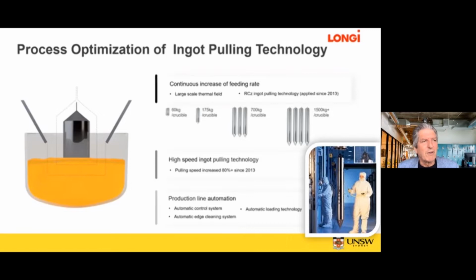So that transition from polycrystalline material, which used a sort of casting technique developed specifically for photovoltaics, back to the monocrystalline wafers as used in microelectronics, involved a return to microelectronics type of processing. So the Czochralski crystal growth is the standard way of preparing ingots for microelectronics, also now for photovoltaics once more. But the thing that's happened for photovoltaics is the recharging of the crucible.